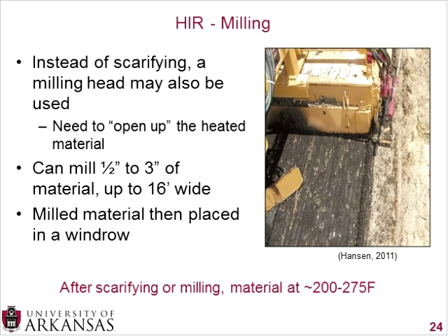So if you recall, after heating, it was approximately 275 to 300 degrees Fahrenheit. And then after the scarifying or the milling, the temperature dropped pretty significantly down to between 200 and 275 degrees Fahrenheit. So still above ambient temperature, but after this milling, you lose quite a bit of your heat.